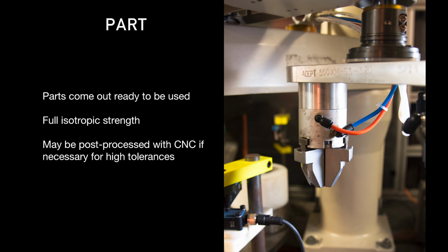Okay, so here's the part on the actual gripper jaw in their line. Parts come off ready to be used. They have full isotropic strength. So if you're familiar with layer at a time manufacturing and 3D printing, traditionally the Z-axis strength is a little bit weaker than the other axes because those layers are being built one at a time. But in the sintering process, you actually get crystal growth that goes across the axes. So your parts are isotropically strong.